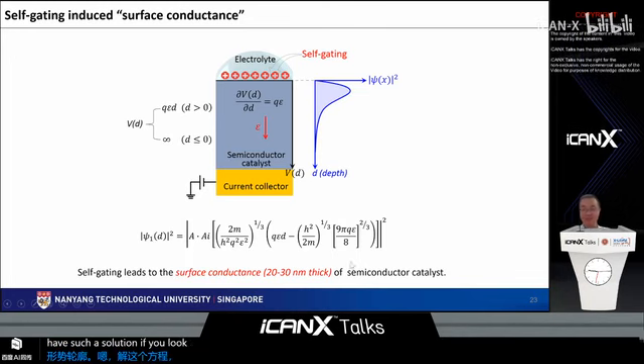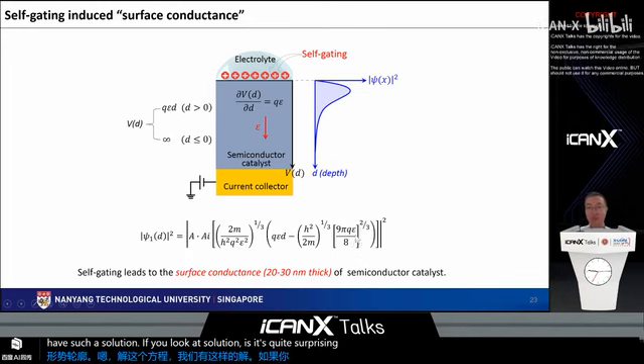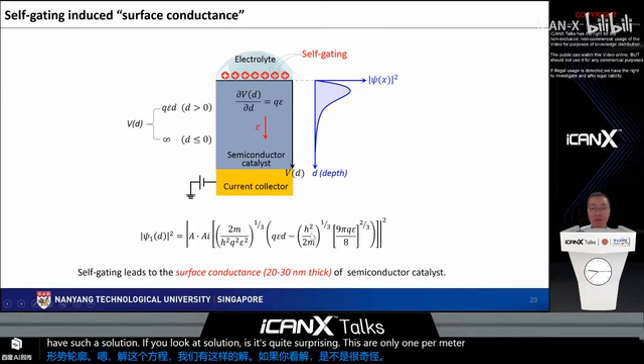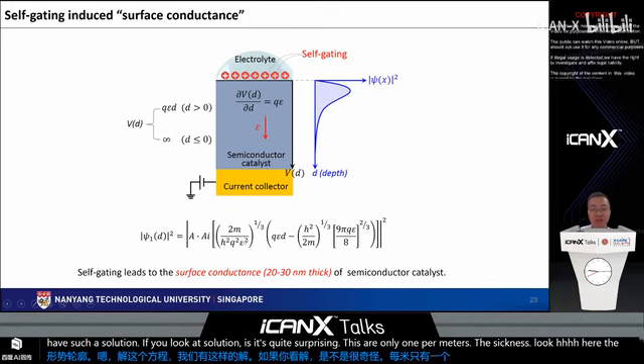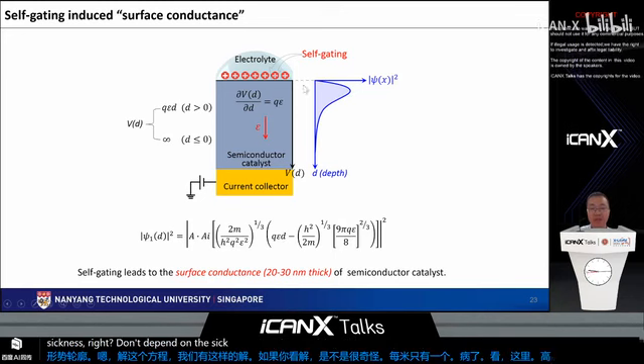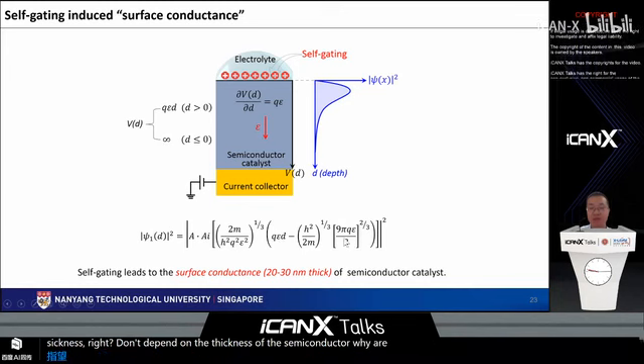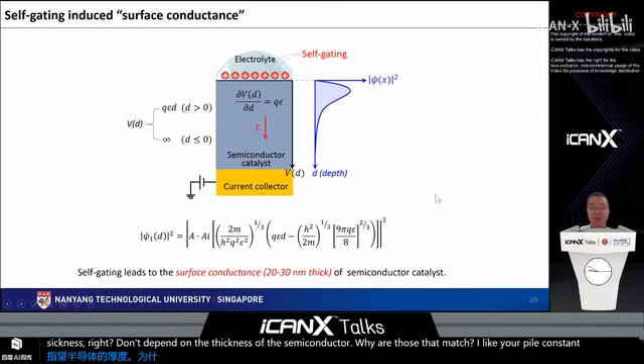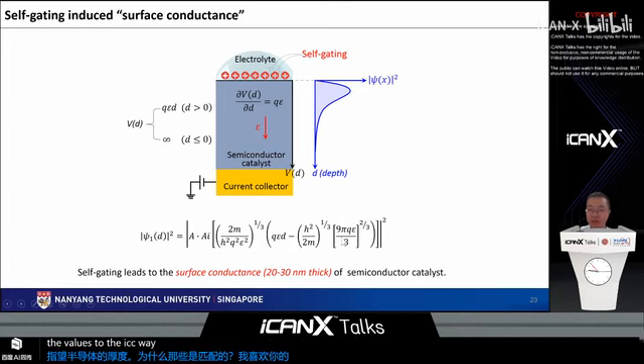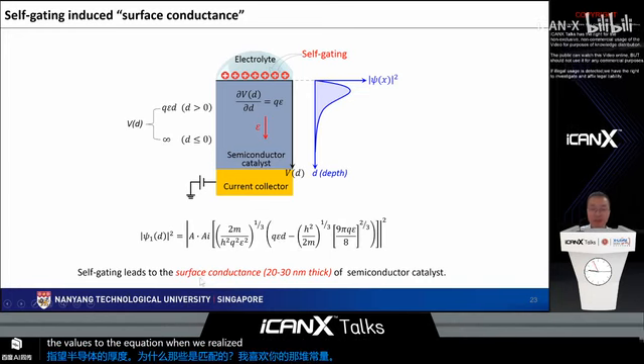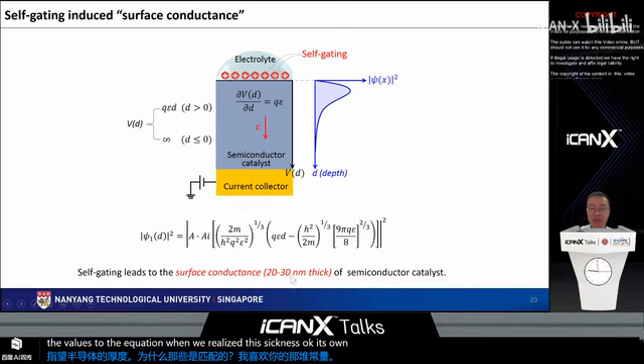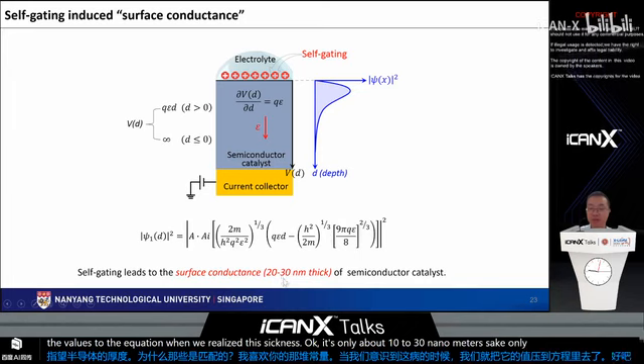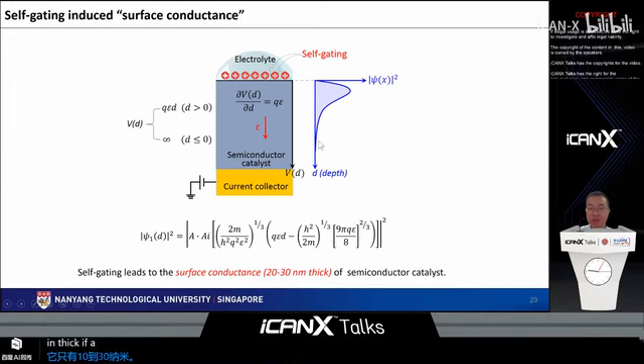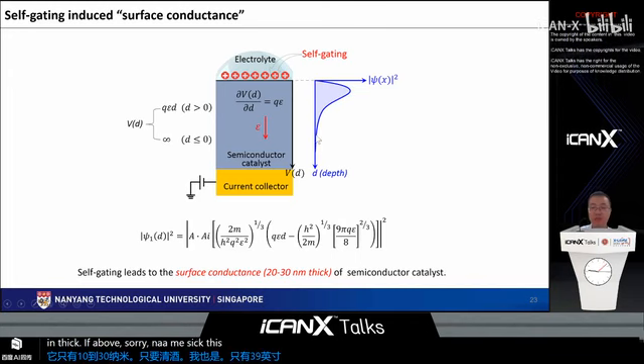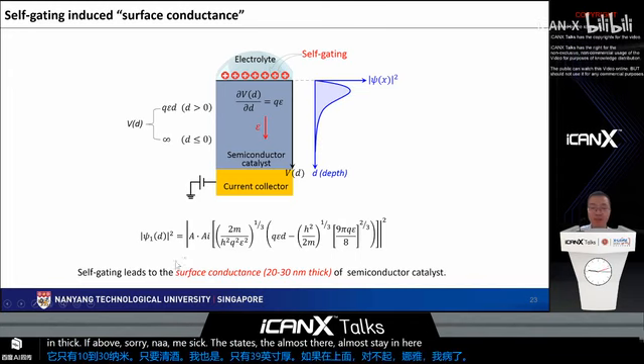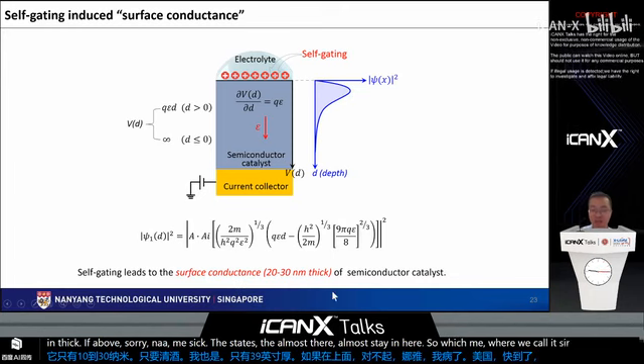If you look at the solution, it's quite surprising. There's only one parameter, the thickness. Look, the D here, the thickness, right? It only depends on the thickness of the semiconductor, while others, like mass, like Q, pi, they're constants. If we substitute the values into the equation, we will realize this thickness is only about 10 to 30 nanometers. If above 30 nanometers thick, there are almost no states in here, which means we call it surface conductance.